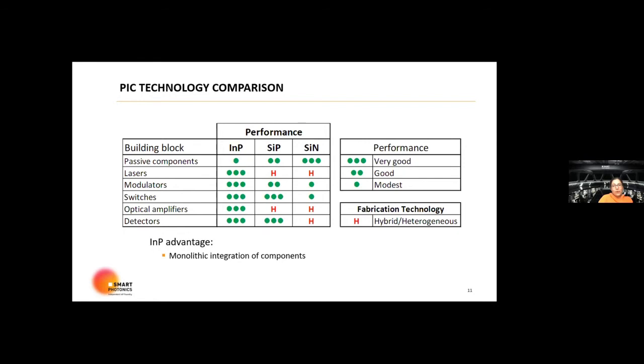Why? Well, because silicon photonics and silicon nitride, these platforms, these materials, don't lase, whereas indium phosphide lases. So you can make lasers, you can make optical amplifiers using indium phosphide. And what this will enable you is to have a monolithic integration of all of your components in one platform, if you were to use the indium phosphide. Again, there are options to mix and match different platforms to take advantage of different performance. But there are obviously costs and benefits to it.